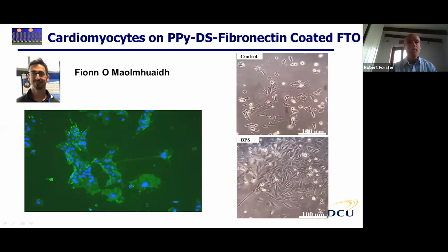Chunyan trained up Fionn in our lab, and Fionn has been able to grow cardiomyocytes on this surface - this is a polypyrrole film that contains fibronectin. What you're looking at is the growth of these cardiomyocytes on that surface, and what's interesting is that you can do the bipolar stimulation and see changes in the cell morphology as you do that. The combination of the conducting polymer sitting on the FTO allows you to control the local potential, and that influences the growth of these cardiomyocytes.